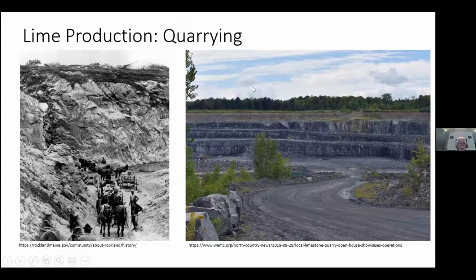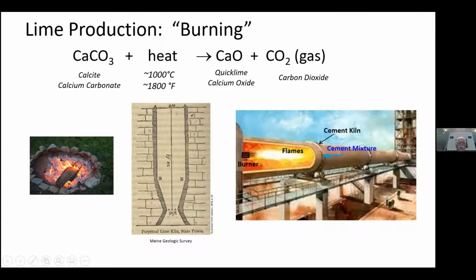So when you produce the lime or burn it, typically you do that in a kiln. Now, kilns run the gamut from the simplest up to the very, very complicated. Initially, probably back into prehistory, lime was just burned in what were called pit kilns. An example of that is over here. All you do there is you take chunks of limestone that you've quarried out and you pile them in with a bunch of fuel.